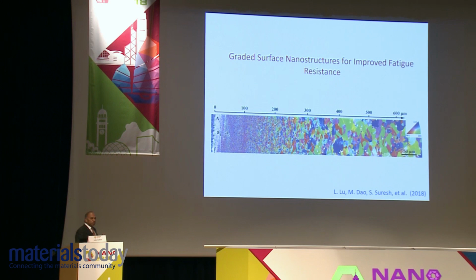So I want to finish with just two thoughts on this, one thought to finish this and a final example. This is some recent work in collaboration with Lei Lu on how we can trick a material that has very poor fatigue response by creating a nanoscale surface layer, but in a large specimen. So here we have many millimeter size specimen, which is microcrystalline copper, but we create a graded layer, an ultrafine layer, and a nano layer at the surface.